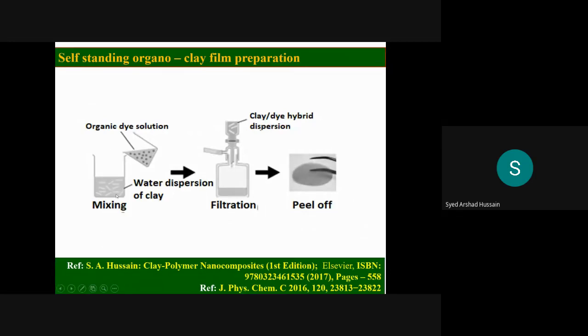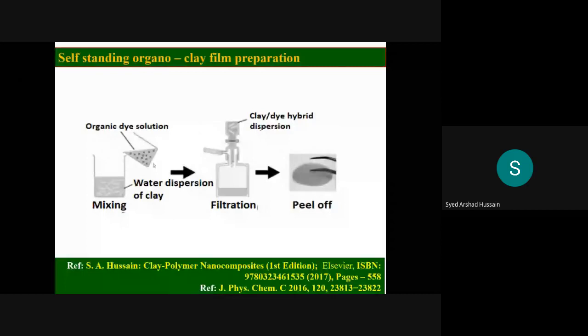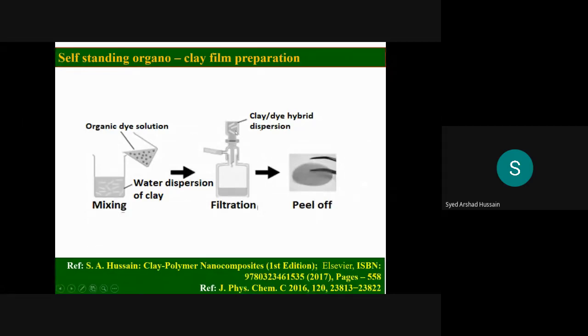Here, what we do, we mix the clay dispersion and the organic material of your interest, put it on the magnetic stirrer, then we use ultrasonication, and then we use a simple system. There is a membrane with a pore size of the order of a fraction of a micrometer, and we put the mixture here and suck using a vacuum pump. Then with time, solvent comes through and the material forms a layer on the membrane.